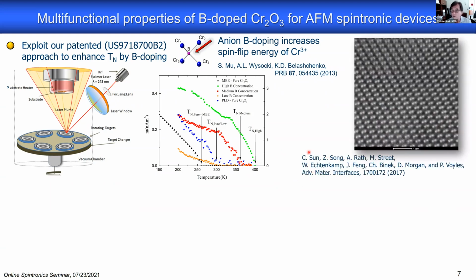Then we brought our films to our colleague these days in the context of C-spin, Paul Voyles, who did his wonderful high-angle annular dark field transmission electron microscopy investigation. Here you see one of his results on one of our boron-doped films. What you can see here are only the high Z elements, the chromium. The method is blind, but you see the nicely arranged chromia. What always surprises and amazes me is you see the buckling structure of the chromium 3+ ions, how they are sandwiched between the here invisible oxygen 2- layers. So the message here is, despite the impurities, despite the doping, the films are very nice structurally.